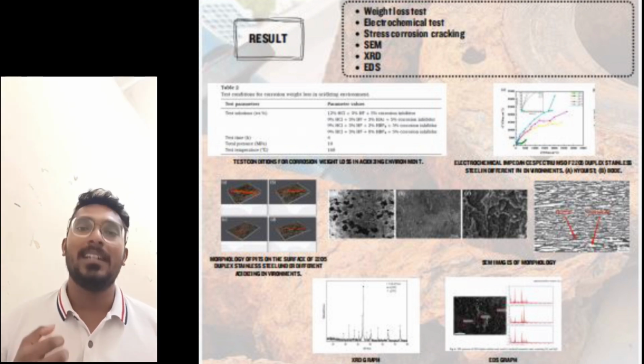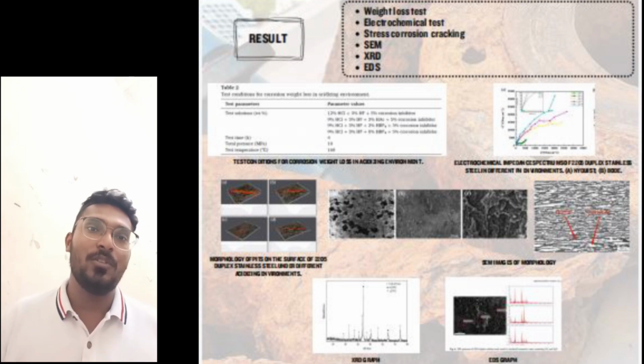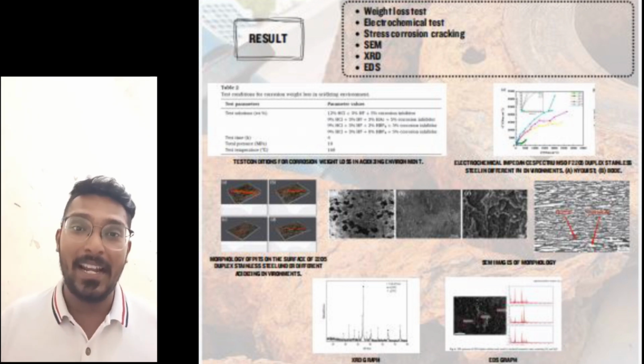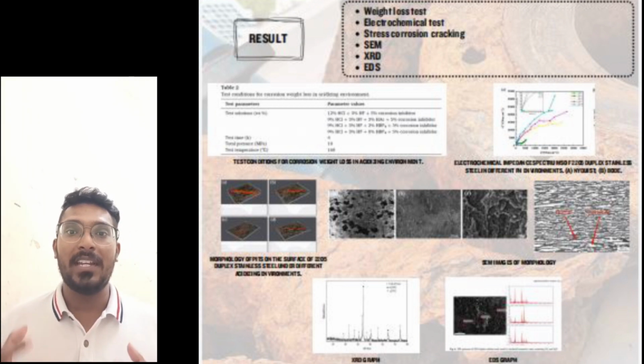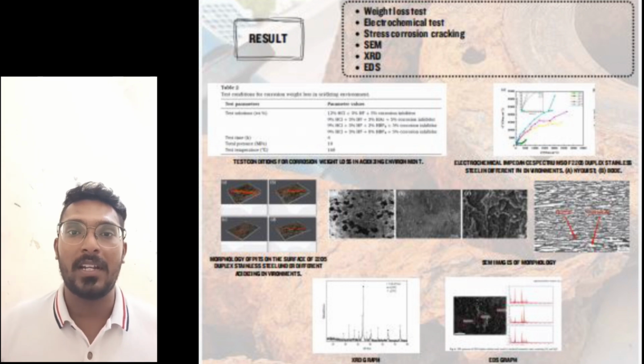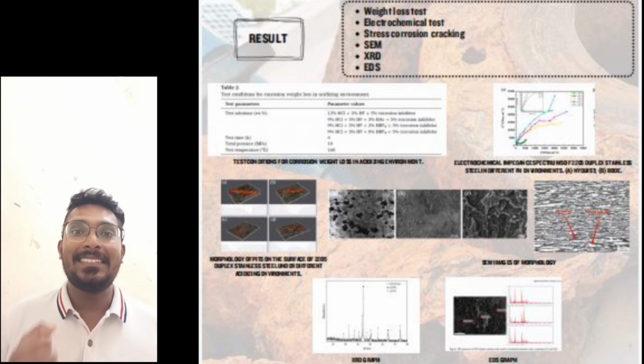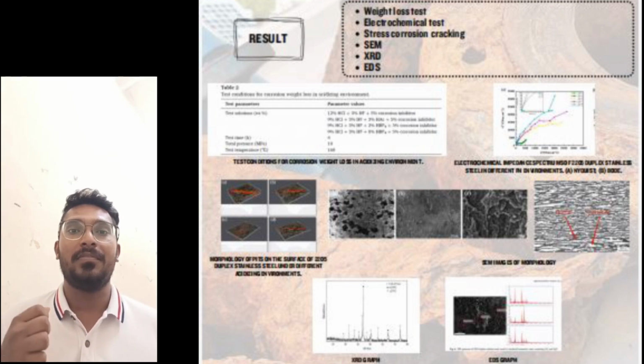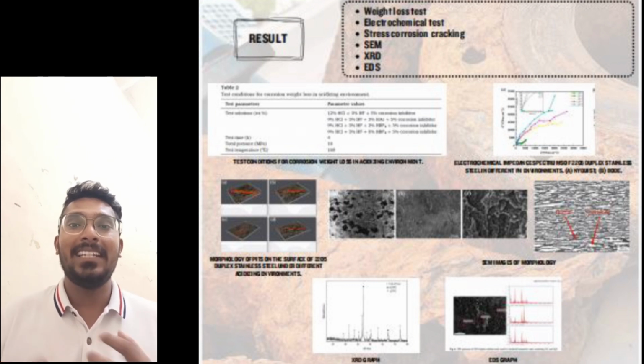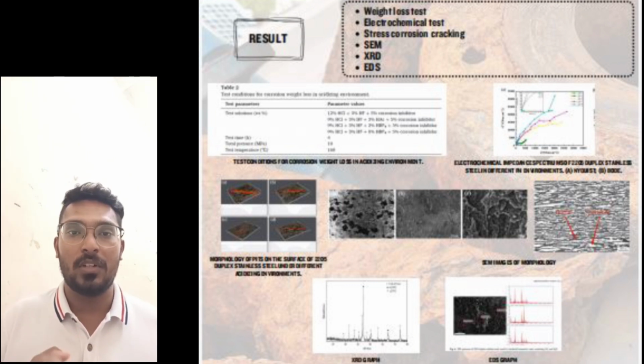Secondly, the electrochemical test shows that the higher pH value improves the corrosion resistance in the weak alkaline environment, with the larger peak value indicating enhanced passivation ability of the protective film. This leads to a reduction in the passivation film dissolution rate and enhances the corrosion resistance in 2205 duplex stainless steel.